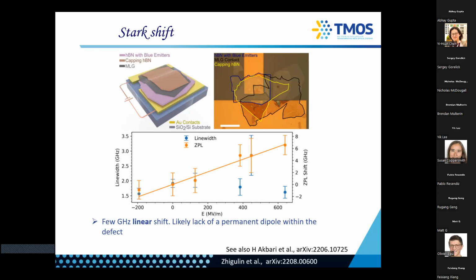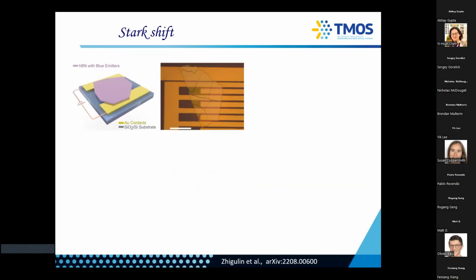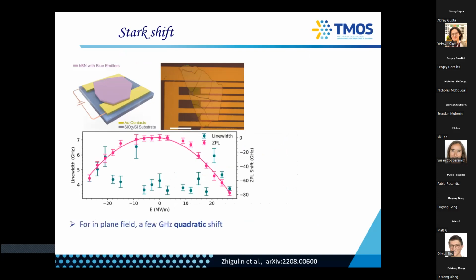This is very small, and the line width is remaining almost the same, so almost 2 gigahertz. So that kind of tells you that there is probably no permanent dipole in the defect. But what you can also do is apply a linear Stark shift, which means that you can put the flake on an interdigitated mask, an interdigitated pattern, and here the results are different.